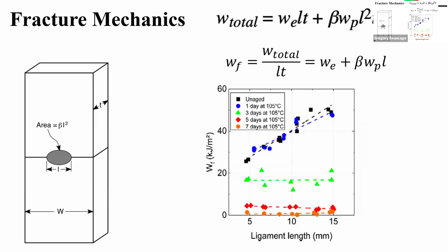So it turns out, if you take plots like that and extrapolate back down to the origin, that gives me the essential work of fracture. And there's a reason for that. That equation up there teaches you that. If I had more time, I'd walk you through it. Again, it's fracture mechanics, which I understand nothing about. There's a contribution of plastic deformation, which is the slope of the curve, and that intercept tells me the essential work of running a crack through the sample.